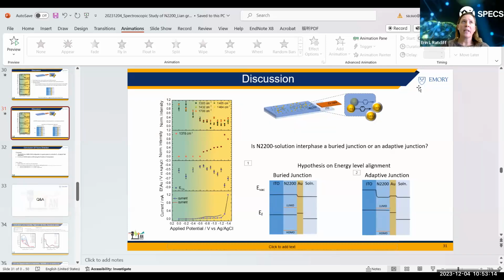So, if we connect that back to some of the early conversation Andrew and everyone was having about, do you have to reduce the entire film to a radical anion before you can make the dianion? And if you truly have aggregates that are easier to reduce, and the gold is below or at the size of the aggregate, the rest of the film, the amorphous fraction, may be there purely as spectator wasted volume, and everything is shooting through just the aggregate, which would explain why the gold appears to be pinned, because it's only interacting with a small fraction of the film population. Yep.